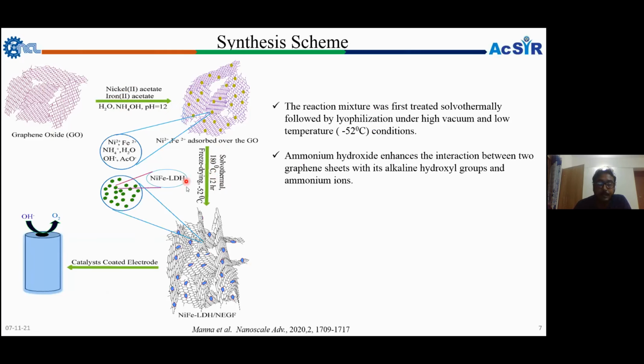drying condition. This is a very important thing, because in most cases after solvothermal or hydrothermal treatment, we go for only filtration of this material, but here, to retain the 3D structure, we applied the freeze drying. Freeze drying is a condition where at low temperature, around minus 50 degrees centigrade, we just apply a vacuum pressure. So whatever the structure is there, the water molecules will be removed, but the structure will be retained.